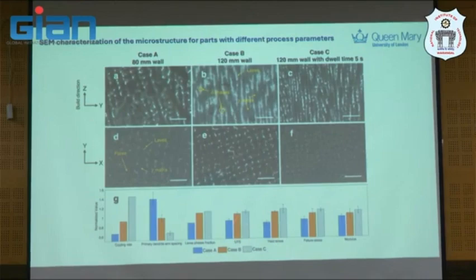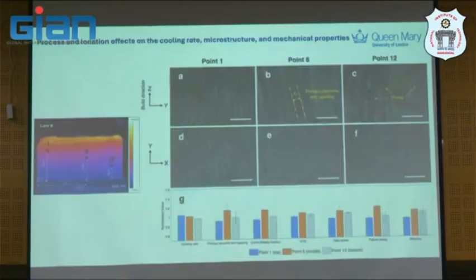So they can predict UTS, yield stress, fracture failure stress, and also modulus here as well. If we look at the specific condition of case B, which is a bigger build, 120 millimeters at 3 locations here, you see the microstructure is not the same at 1, 8, and 12 here. And these contribute to different property sets that they can predict here. It's quite encouraging that data from this data-driven approach can provide such insight in a rapid manner. Again, you will see now that data-driven is not just data. It means something for the manufacturing process. That's what we want, actually.